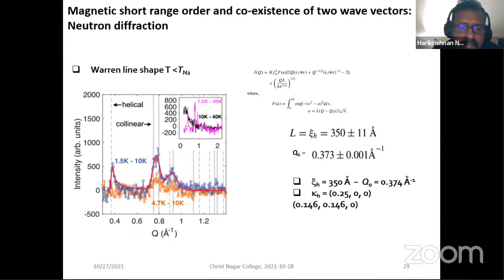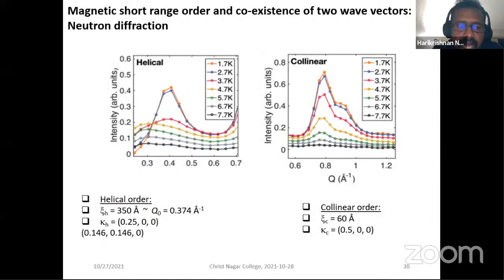But then this vector pertains to the magnetic moment of this system, a cobalt 2+ magnet arranged in space. So we see that there are two of them, and it is understood from how the diffraction pattern changes as a function of temperature. In the case of helical, you can look at the curves, you don't see a peak until 3.7 Kelvin. That's the red line, which is also very broad. When the temperature goes below that, all of a sudden you see a peak which is increasing, the blue and the orange. And that is the helical order that happens at lower temperature.